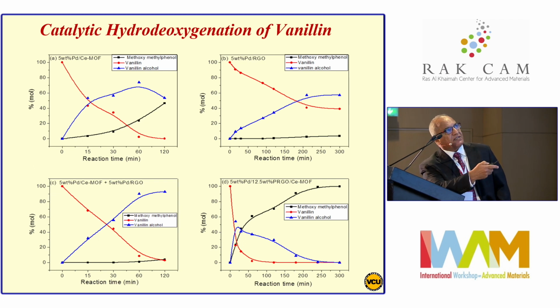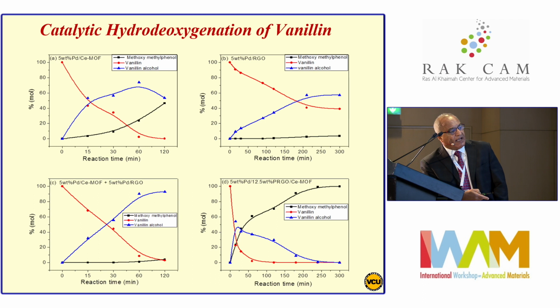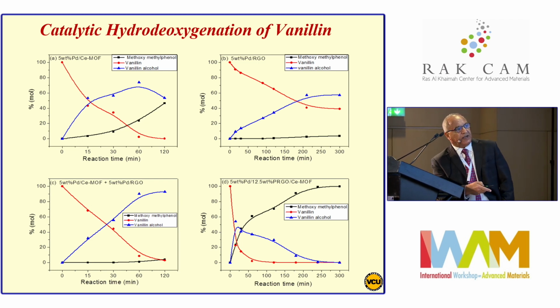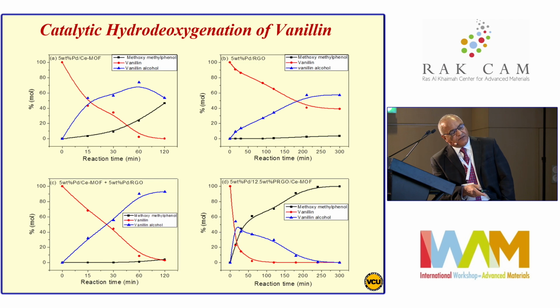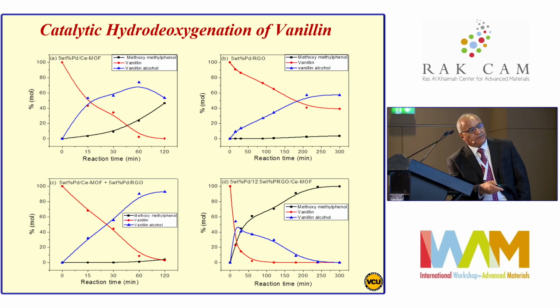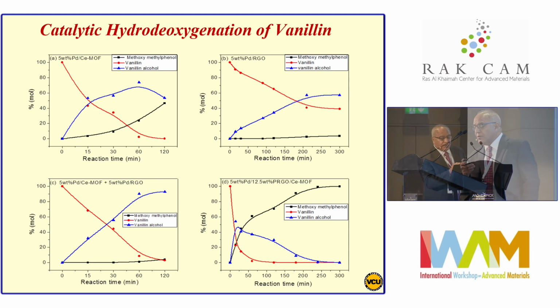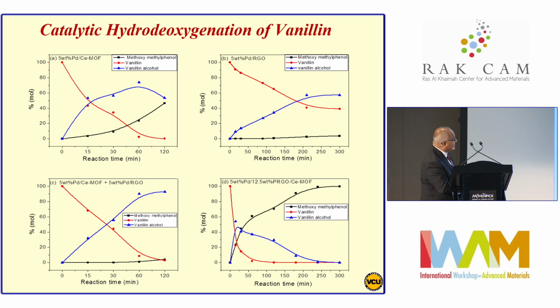If you have a physical mixture of graphene oxide and the cerium MOF, you see basically what you see in these two additions. Just adding these two results, you again see very little of the final product, methoxyphenol, and most of the product goes to the undesirable vanillin alcohol. However, if you have the hybrid structure that we constructed, you can see that the vanillin goes down, and although the vanillin alcohol is formed, it reacts quickly in a few minutes, and it starts to form the final product that we like to have, which is the methoxyphenol, and reaches 100% within 200 or 250 minutes. So it appears that the hybrid structure is really working in producing the final product, methoxyphenol.